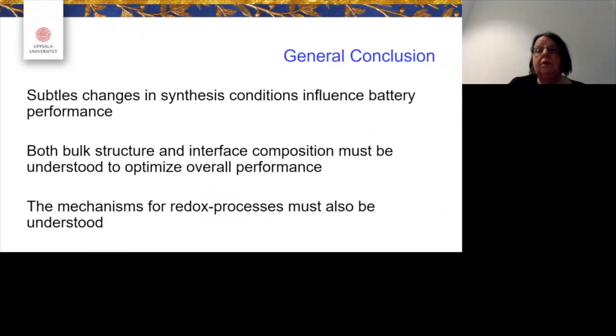So to give a general conclusion, it should be clear that subtle changes in synthesis conditions, and there are other examples that are even more subtle than this, influence battery performance. So particle size, particle orientation, particle morphology, and of course the atomic structure plays a big role. And we must know both the bulk structure and the interface composition to optimize the overall performance. We must really understand these redox processes.